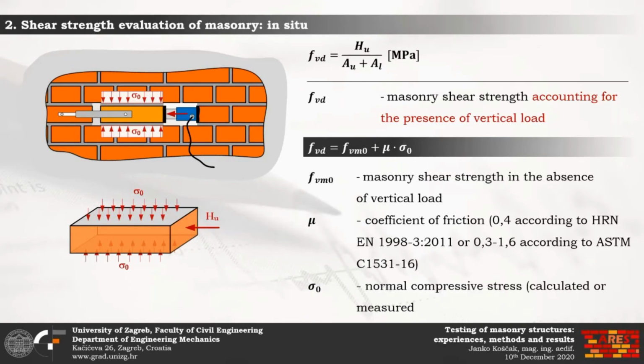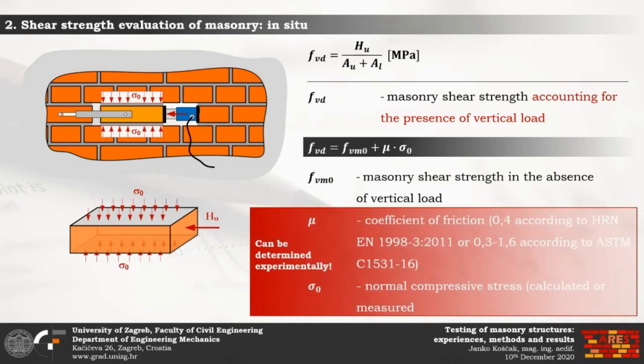A value that is more useful in design is the joint shear strength without the influence of vertical load. This is f_vm0. However, even with the simple shear test, the value of joint shear strength can be assessed if the value of the friction coefficient is taken from the literature and if normal compressive stress is taken from a numerical model of a building. Additionally, better information about the masonry shear strength could be obtained through experimental determination of these parameters, and that can be done with flat jacks.